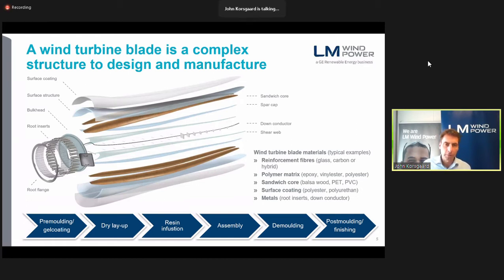Then we also have some metal parts. We have a lightning protection system that can either be a mesh, a copper mesh on the surface, on the outer part of the blade. It's not a solution that LM uses. We use a down conductor system as shown on the picture here. And then finally in the root end you will have either bolts or inserts, as we use, in order to attach the blades on the hub.